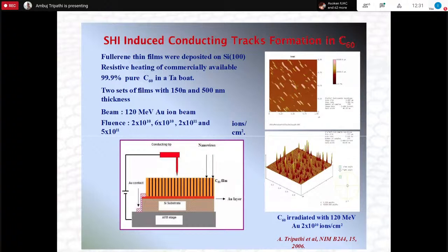So wherever the ion beam had hit, what you are seeing, those bright marks, are where the ion has passed through and has changed the conductivity. So the bright spots are the higher conductivity, and the overall black background is C60, which is supposed to be insulating. Wherever the ion beam has hit, it becomes conducting. And one important thing is you will see this fluence here. It is written 2 into 10 to the power 10 per centimeter square. Whenever you show this type of result, the question always comes: how are you sure that this is because of the ion beam track?